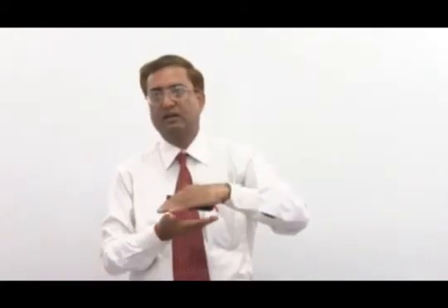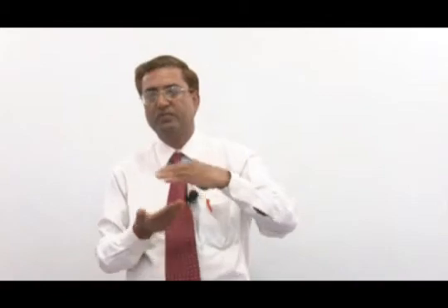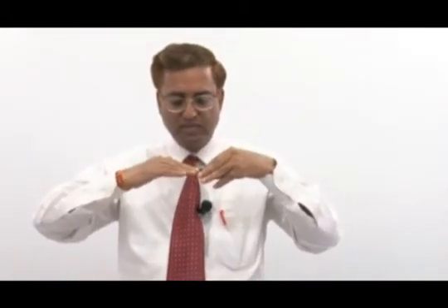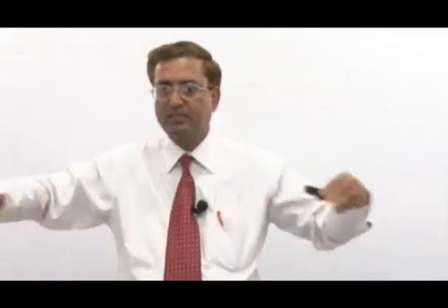So, because there is a compressive stress, if I call it sigma y, and there are the interfaces, the upper die and lower die, two interfaces. If mu is the coefficient of friction, then the frictional stress is mu sigma y, and the material is going to flow in this x direction.